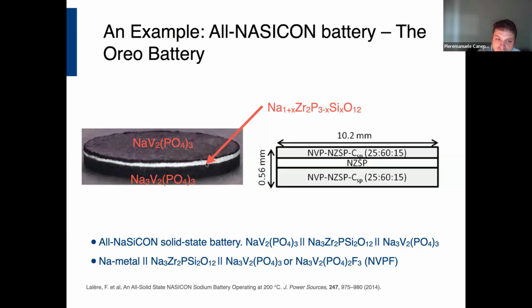Now, the beauty of this battery is they are monolithic, right? Monolithic in the sense that you form them in a spark plasma sintering machine, right? So you deposit a composite, as you can see here, of NVP, which is sodium vanadium phosphate, together with some carbon black and some sodium zirconium silicon phosphorus Nasicon, with the general formula that you see here. And all together you form this initial pellet in the spark plasma. Then you deposit the powder of NZSP, which is the Nasicon separator solid electrolyte. You perform a second sintering, and then you perform a third sintering, in which you fuse all the three materials, forming the Oreo battery. So in this sense, this battery doesn't require any pressure stacking.